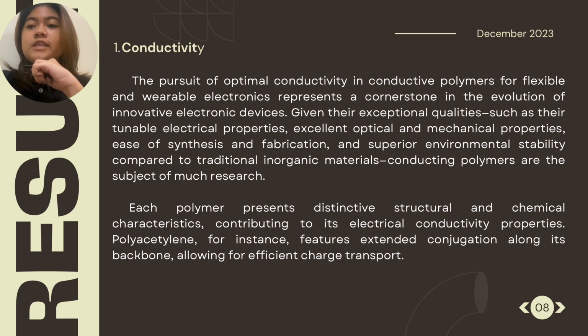Ouyang's further study in 2021 reinforces PEDOT:PSS dominance in practical application due to its high conductivity, thermal stability, and solution processability. Unlike many intrinsically conductive polymers or ICPs, PEDOT:PSS water or polar organic solvent dispersibility, facilitated by PSS's role as a polymer surfactant, overcomes barriers in processability.